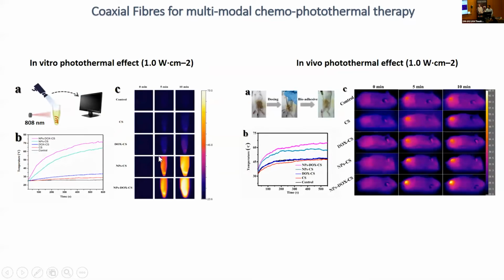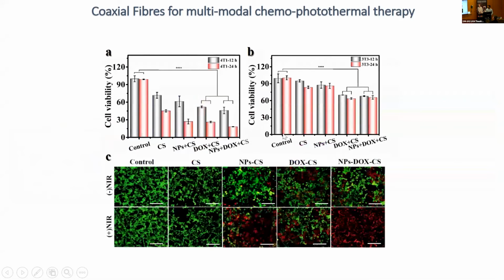And then we've done both in vitro and in vivo experiments where we shine them with near-infrared laser to see how the temperature will change. Basically, we used 2 centimeters of these fibers, and when we did the in vivo subcutaneous models, you could see that they were able to raise the temperature up to 63, 64 Celsius. Then we've done some in vitro studies on these fibers using breast cancer cell lines, 4T1 breast cancer cell lines.